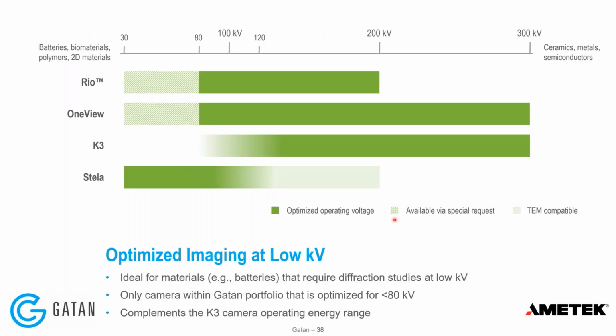Okay, one other important point to make about the Stela camera is that because it uses hybrid pixel detection technology, it is optimized for low kV imaging. So looking at our camera portfolio, Rio and OneView are scintillator-based cameras that are optimized for 80 to 200 or 300 kV regular imaging. K3 is our monolithic direct detection camera that is a CMOS sensor where electrons pass through the sensor. And what that means is that it performs better and it gives you higher DQE, higher signal to noise ratio at higher kVs. So it's optimized for 200, 300 kV. And really, we don't recommend using it below 80 kV.